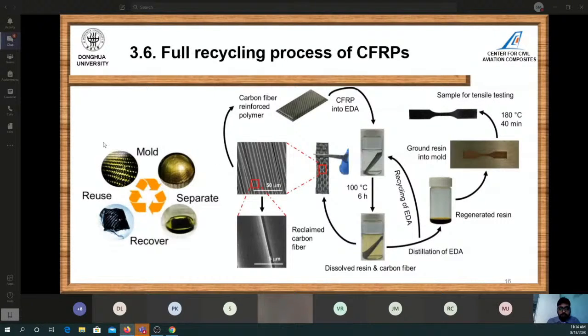And this is the full recycling process for the CFRPs, carbon fiber reinforced plastics. Like what we have done, we dissolved this coupon into the resin, and we extracted the carbon fiber out, and tested the SEM, to see whether we can reclaim the carbon fiber from the composites.